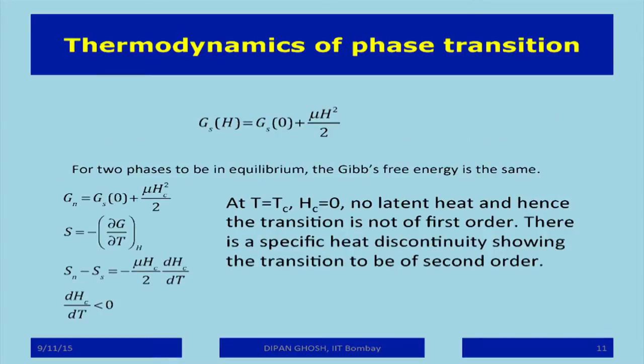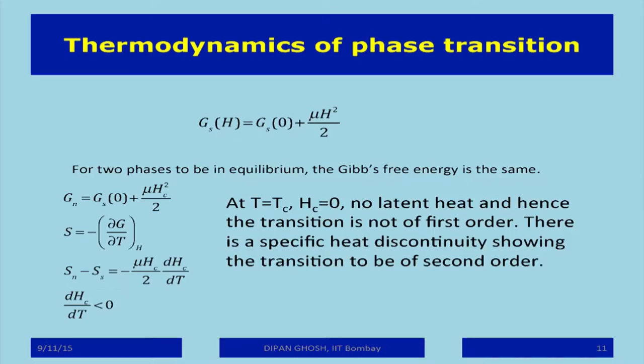Now, supposing I want to find out when the two phases, the normal phase and the superconducting phase, will be in equilibrium. I know at temperature TC, the two phases are in equilibrium. Alternatively, at any given temperature, if I apply a magnetic field of strength HC, the superconductivity will be destroyed, it will go to a normal state. So therefore, the normal state is in equilibrium with the superconducting state at H equal to HC. So my normal state Gibbs free energy is given by the same expression with GS0 plus mu HC square by 2.